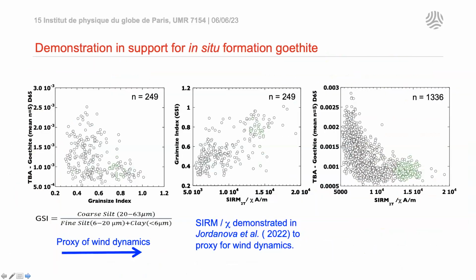So on the left-hand side of the plots, we have goethite content, the DR derived, and it's plotted against a grain size index. So we would expect, if the goethite was being brought in with the parent material as coatings, that it would have some kind of correlation with our parent material sedimentological indexes.